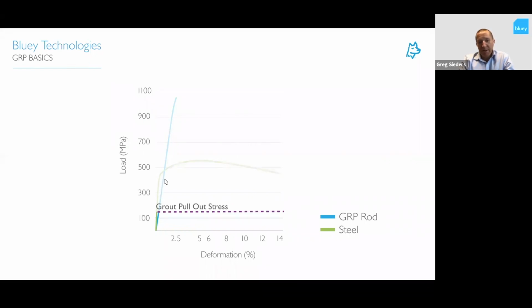The blue line here, I don't know if you can see very well, and the green line is illustrating a steel bar. So you can see when it gets close to about 400 MPa, you start to put your steel bar into yield and you'll get your deformation. What happens with the GRP bar, because you've got a lower modulus than a steel bar, you'll start to get elongation in your bar. So you get your signs of failure, you'll get cracking in your shotcrete and all those sorts of applications. But generally, your soil nail will pull out of your ground well before you get to that application or getting up to your failure of the GRP bar.